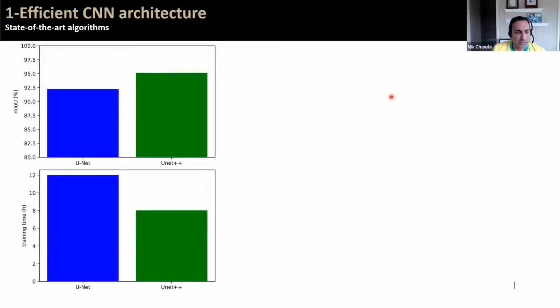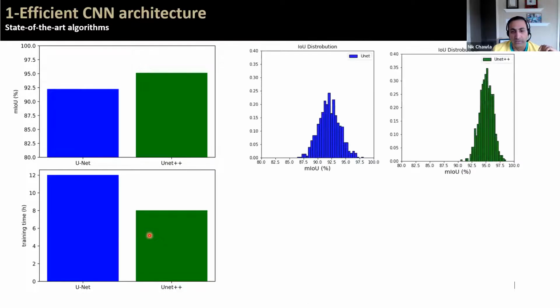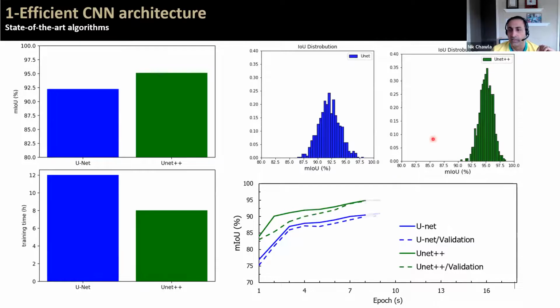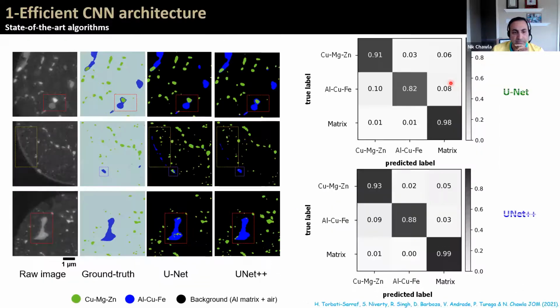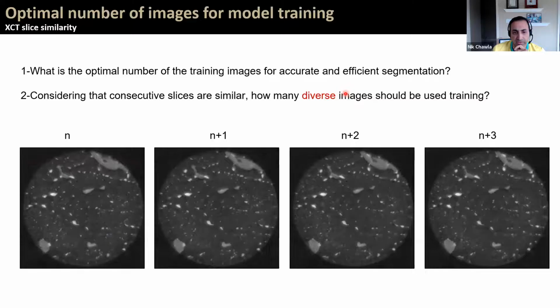Okay, so we compared UNet and UNet++. We have better accuracy with the UNet++, the training time is lower, and we get a fairly nice distribution in the MIOU, which is the measurement of the area of overlap. And here you can see some actual images. The raw image is on the left, and then the ground truth, which was manually segmented, is the next column. And you see UNet and UNet++, and both do a fairly decent job. But again, the UNet++ is a lot more efficient and can be trained in a lot lower amount of time. So we can get most of the phases again, the Cu-Mg-Zn, the Al-Cu-Fe, and the matrix.